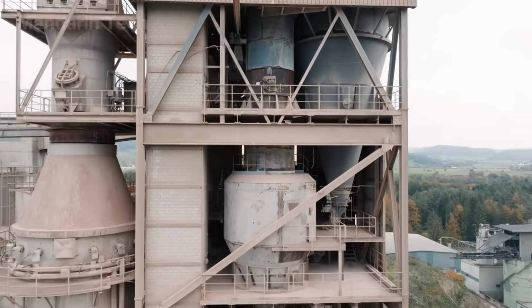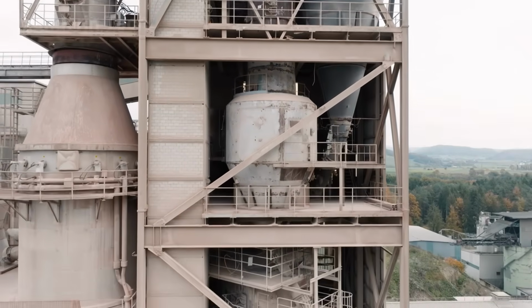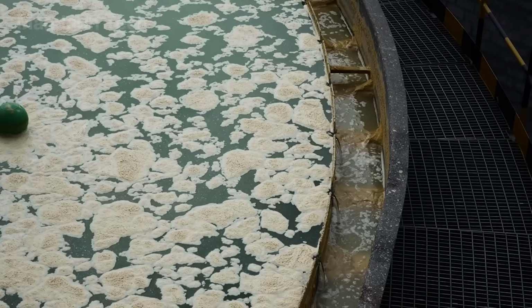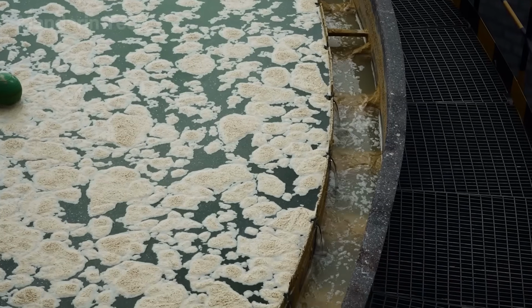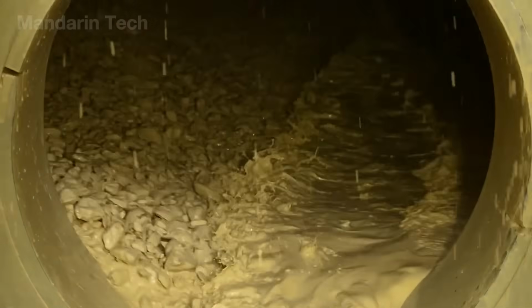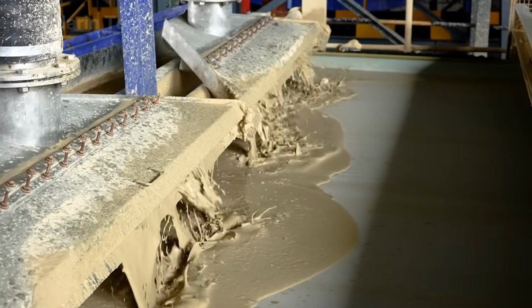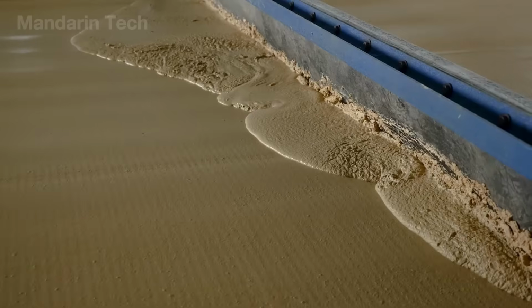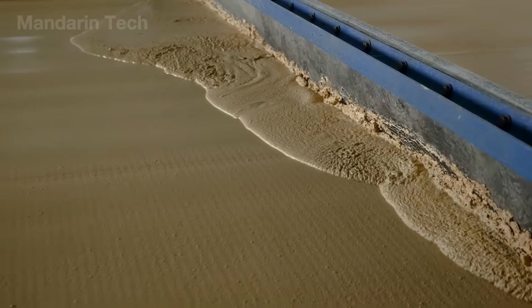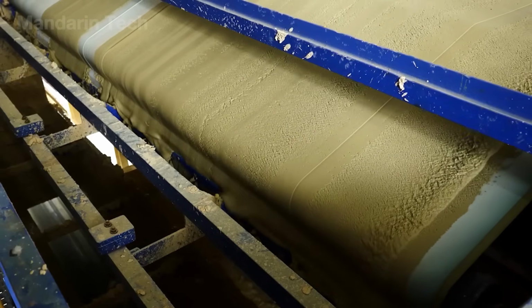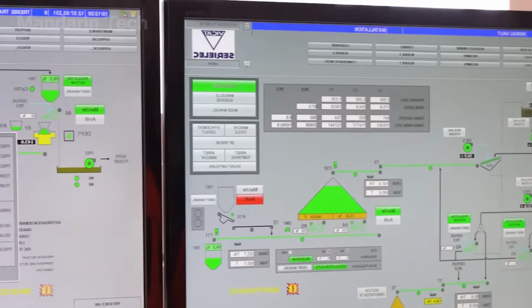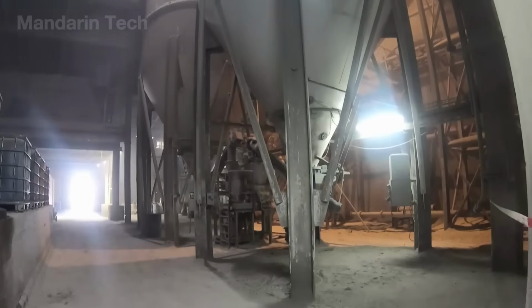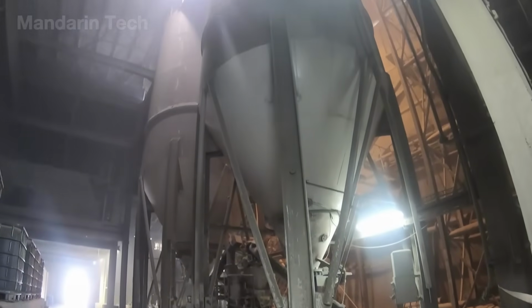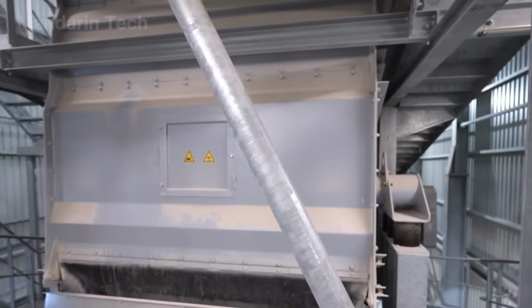Some older production lines still use the wet grinding method, adding water to create a slurry. This approach makes chemical control easier, but consumes significantly more energy, so it is gradually being phased out in favor of more efficient dry grinding systems. Throughout the entire process, all operating parameters, including feed ratios, grinding speed, fineness, and gas temperature, are monitored in real time by the SCADA system to ensure the raw meal remains stable and consistent before moving on to the next